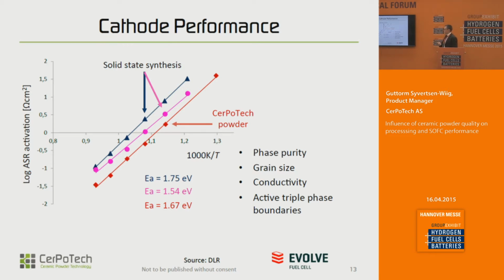This is LSCF powders, lanthanum strontium cobalt ferrite, showing that different synthesis routes give different results, and also these results are probably different if you try the same powder another time due to the processing conditions.